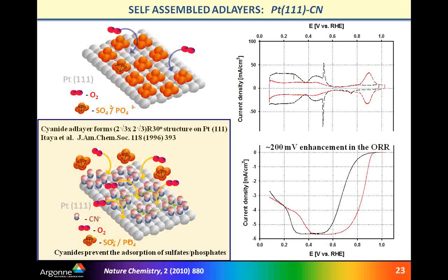but somehow not to allow a big phosphoric acid or sulfuric acid anions to penetrate and to be absorbed on the surface. This is almost like a shielding way how one can make high selectivity to be selective only for the oxygen reduction reaction. And for this system somehow we manage to go from very inactive platinum 111 in sulfuric acid solution, which is the black curve, to the red one, which is activity on the surface, which is covered with cyanide, the activity is almost identical as in the case of perchloric acid.